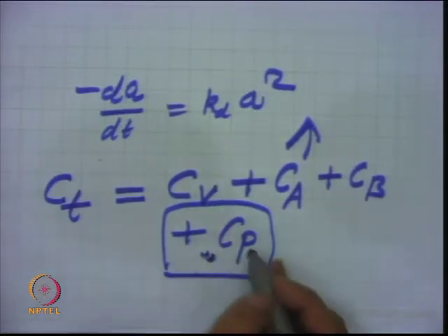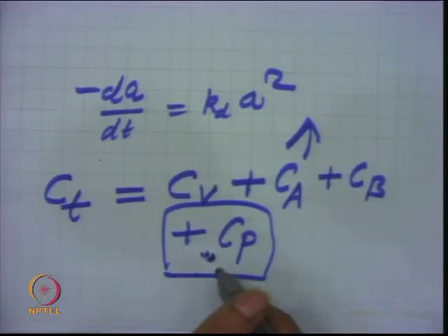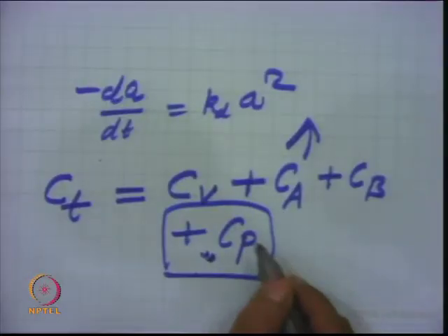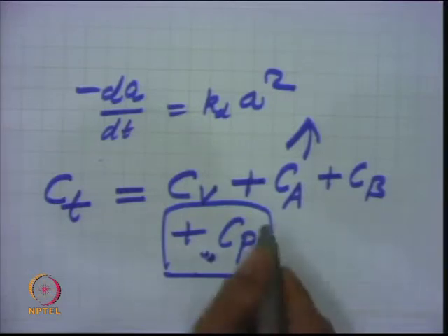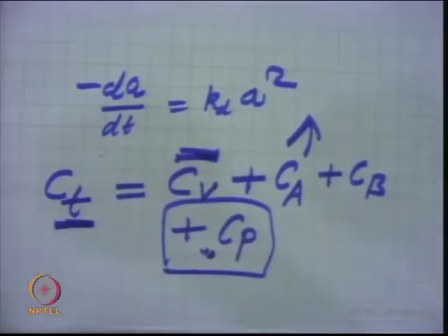So, this C_p remains in the denominator of the main reaction if you write the expression in terms of the adsorbed species concentration. So, that is generally not known. So, we write it in terms of some activity function, that is how much the rate is lowered because of this poison precursor with time on stream. This is what is actually decreasing the rate, because the poison is covering the active sites of a catalyst. So, the available vacant sites are continuously decreasing with time on stream. So, this is C_t0 in this case, but with time this C_t is decreasing because C_p is continuously blocking the active sites of the catalyst.